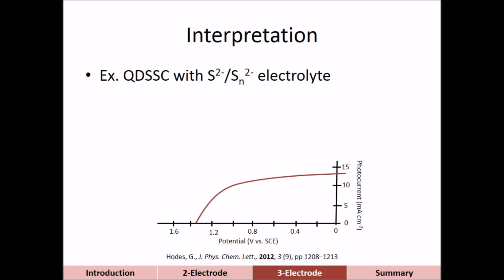So let's look at an example IV curve obtained using a 3-electrode cell. So the potential that we see along the x-axis is now the potential versus the reference potential. It's not absolute cell potential. So depending on the reference electrode we've chosen, this can change significantly. Therefore, to extract meaningful information about the working electrode performance, we have to convert the potential scale into a more meaningful one.